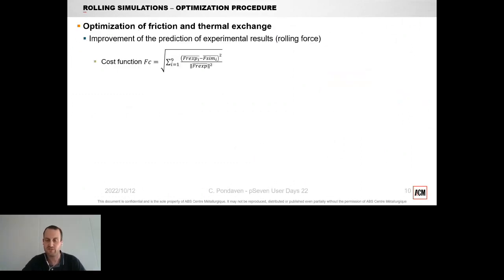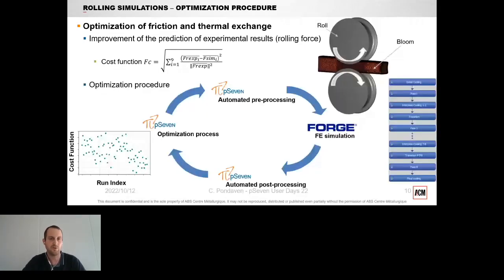The optimization procedure will consist of the improvement of the prediction of the rolling forces using the simulation model, and we compare the simulated forces with the experimentally recorded forces. To do so, we construct an optimization procedure using P7. We have first the design space exploration and the selection of the different parameters performed by P7, an automated pre-processing phase that will set these different parameters into Forge. Forge is used to perform the finite element simulation with different cooling and rolling phases and interpolation between two rolling phases. And then the results of all these phases are automatically post-treated using P7 to compute the cost function and output it into the optimization procedure to pursue the study.